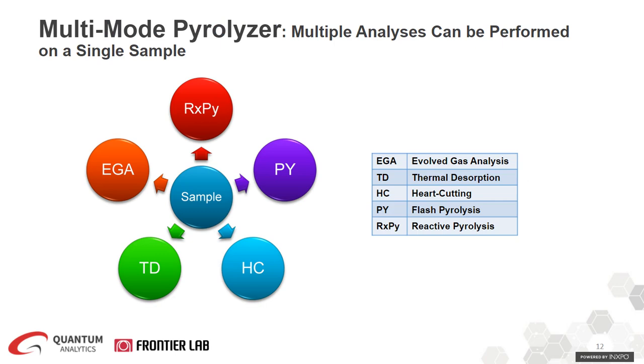Okay, now let's start talking about the multi-mode pyrolyzer and how it works. So as the name says, using the multi-mode pyrolyzer, multiple analyses can be performed on a single sample. This is actually one of the advantages of our pyrolyzer, where the furnace can be used for other analytical techniques in addition to flash pyrolysis. So the multi-mode pyrolyzer can be used for both thermal desorption and pyrolysis by identifying the volatiles, additives, lighter components, as well as oligomers, heavier and polymeric compounds. So you can perform evolved gas analysis, EGA, thermal desorption, flash pyrolysis, reactive pyrolysis, and even heart cutting technique. And we'll discuss each of these techniques in a few minutes.